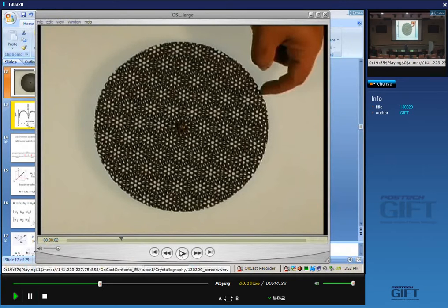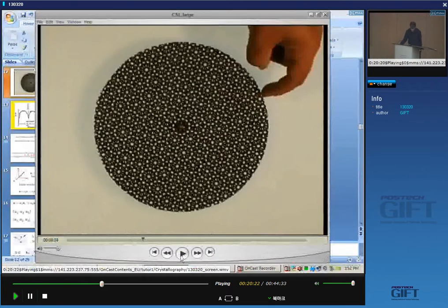So at particular values of theta, you get a certain fraction of the lattice points which are exactly matching between the two crystals. When I put the two crystals on the same origin and let them penetrate space, you find patterns where you get a high density of coincidence points. And those patterns are called coincidence site lattices, okay? So you can see, for example, here, there's an even higher density of coincidence points. So when we get to those special orientations of theta, the boundary gains a lot of coherency.